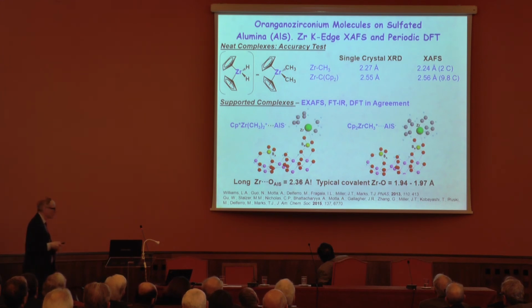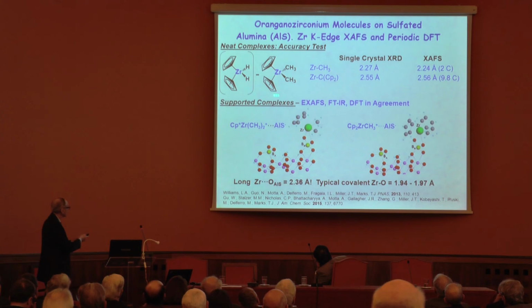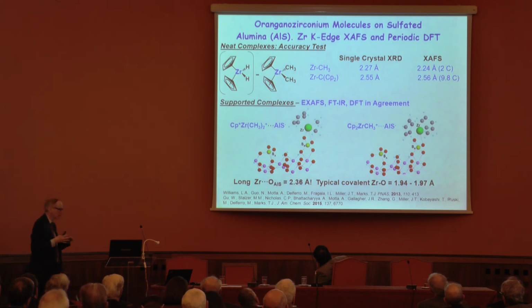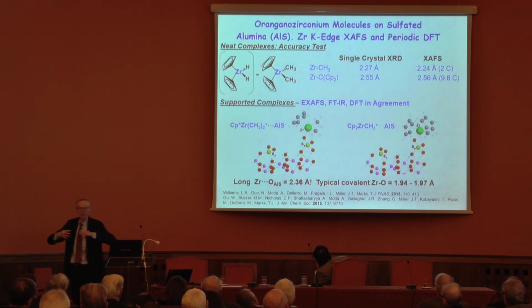So, final question. We go back to the issue of the Haber process and all of these heterogeneous catalysts. What would happen if we put one of these molecules on a surface? It turns out to be a very particular kind of sulfated oxide surface. We use XAFS, a technique to look at the groups around the zirconium, and this just shows you single crystal X-ray, and XAFS gives the same answer. I put it on the surface, and it goes crazy. It's more reactive than anything we've ever been able to get our hands on before.